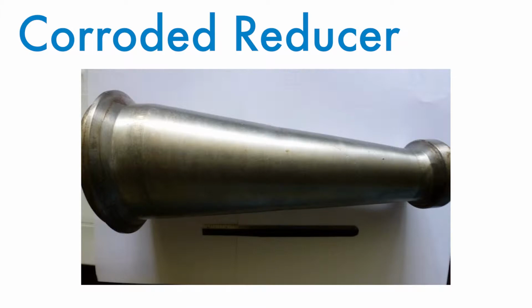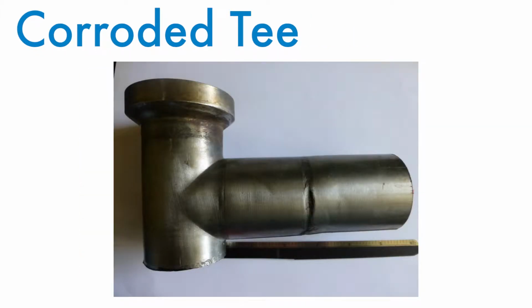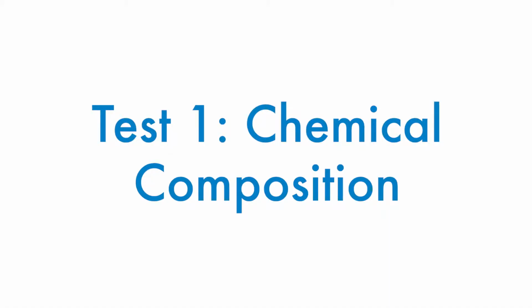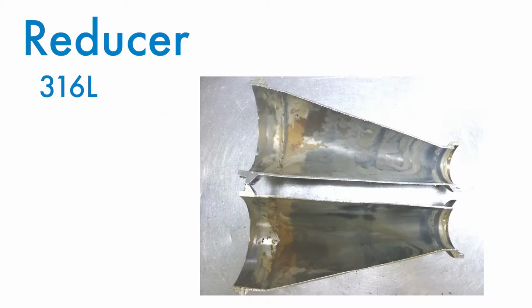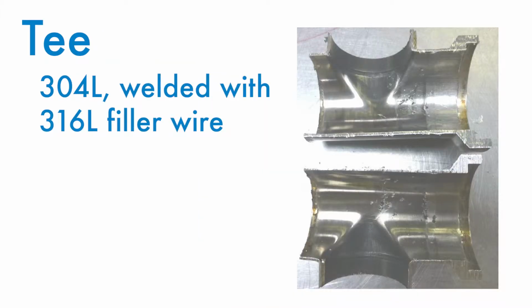To better diagnose the problem, CSI obtained a corroded reducer and T from the facility. After visual inspection, CSI sent these parts to an affiliate lab to determine the cause of corrosion failure. Test results from the lab found 4 issues with the parts that were causing them to leak. First, the test showed the chemical composition of the leaking parts. It revealed that the reducer was fabricated and welded using 316L, while the T was fabricated with a lower grade 304L and welded with 316L filler wire.